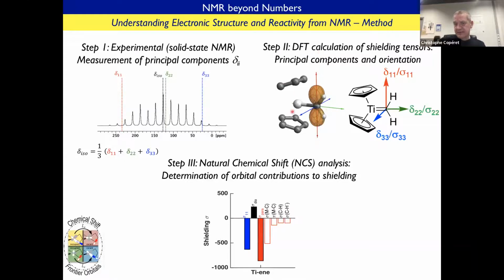We are going, in a second step, to calculate this chemical shift tensor by DFT calculation at very high level. And this will allow us to orient the chemical shift tensor with respect to the molecular frame. In particular, we want to know what the direction of the delta 11 component is with respect to this molecular frame. And then, based on natural chemical shift analysis, we are going to ascribe what is giving rise to this very large chemical shift value to specific molecular orbitals. This is going to be the methodology that I'm going to use throughout my presentation today. And from that, we'll be able to relate a chemical shift value to specific frontier molecular orbitals and their contribution to the chemical shift.